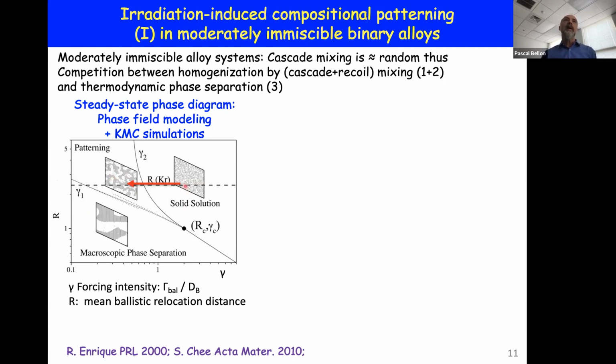So after obtaining these results with the experimental validation, what we did is that we picked an alloy system and an ion, so that R is fixed. And the simplest thing to do in experiment is to increase the irradiation temperature. At very low temperature, thermal diffusion is very sluggish, so this reduced forcing is very high. So we'd start here on the right side. And then as we increase temperature, we increase thermal diffusion, and we expect the system to